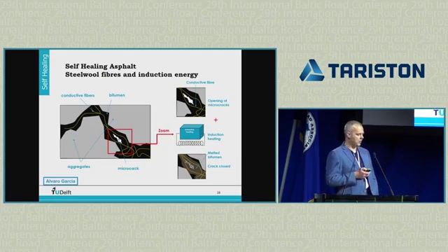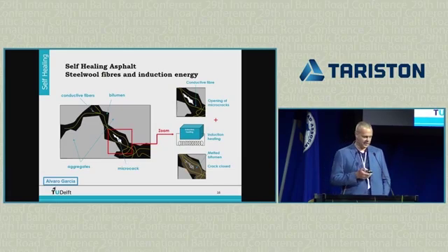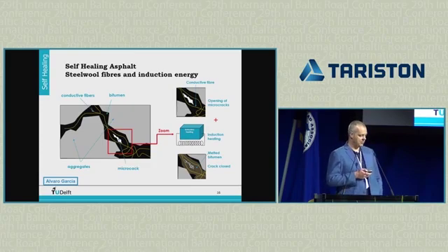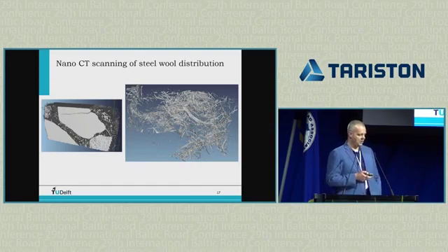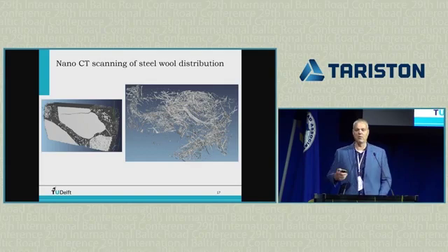So here you see the principle. You have these fibers mixed into the asphalt. If you get a small crack in the system, you come with your induction coil, you heat up the material, so from the inside out, it heals up. The steel wool will melt the bitumen and that will close the cracks. So here you see a sample that we put in a CT scanner to see the distribution of these very fine steel wool particles in the material. So it's very well distributed in the material.